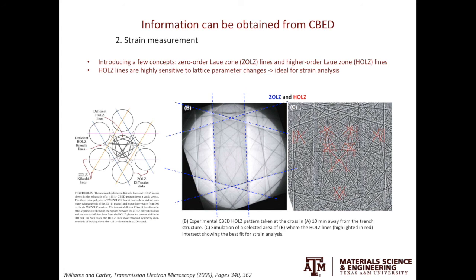You may wonder why using the higher-order Laue zone lines instead of the zero-order Laue zone lines to determine the strain in the specimen. This is because higher-order Laue zone lines uses a much larger G vector, so it's very sensitive to the strain in the material. Even very small elastic strains can be better captured.